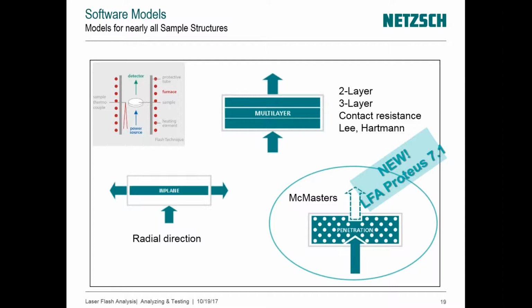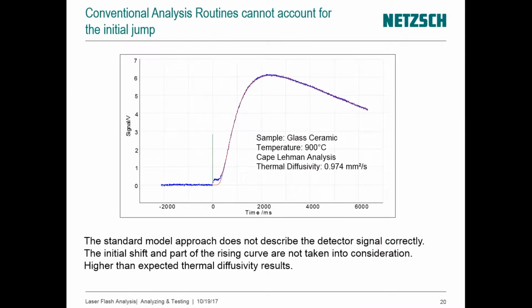These are all the grounds we are covering before looking at actual test data. One thing that is very common when it comes to ceramics is that they tend to be semi-transparent or even transparent to the wavelengths of the laser. If that's the case, then you notice, as shown here with the blue raw detector signal, that at the time of the discharge of the pulse, the detector signal suddenly increases too. Following that sudden jump, you see the expected temperature excursion, the excursion of the signal from the detector.